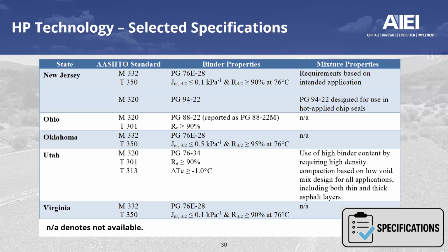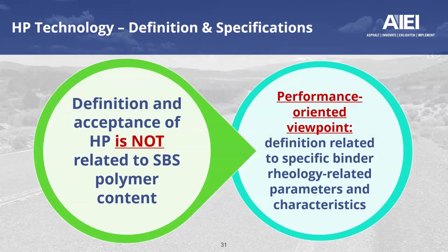Going to another example, Utah used AASHTO M320 with the PG76-34. They only have a requirement on the percent recovery of a minimum 90%. They do have a requirement on their Delta Tc, but we will notice throughout the case study that they also have requirements on the mixture and not only on the binder. So all I'm trying to say is the definition and acceptance of HP is not related to SBS polymer content, but it is a performance-oriented viewpoint. The definition is related to specific binder rheology-related parameters and characteristics.